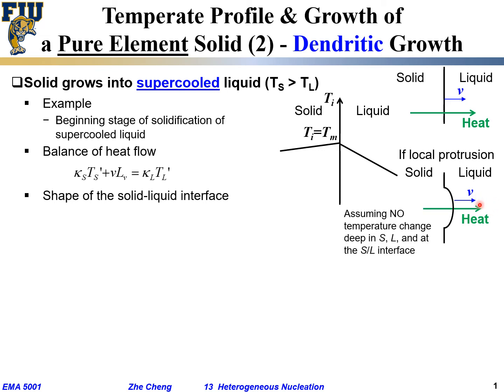The velocity of the interface is the same. We assume deep within the solid there's no temperature change, and deep within the liquid there's also no temperature change. Right at the solid-liquid interface, temperature equals the equilibrium melting temperature. On the left side within the solid, the distance is getting larger while ΔT is the same, so the temperature gradient within the solid gets smaller. For the local protrusion region within the liquid, distance gets smaller while ΔT remains the same, so the temperature gradient on the liquid side gets larger.